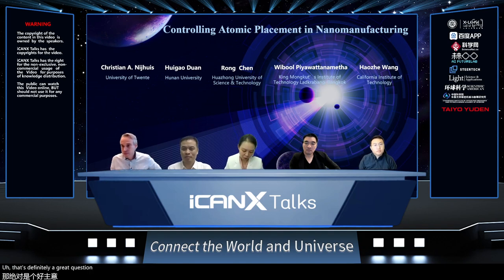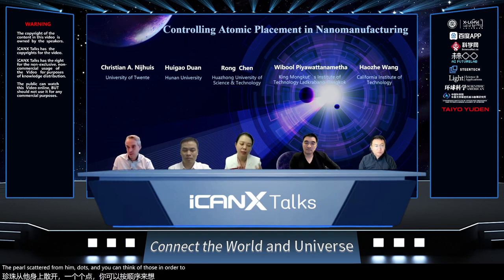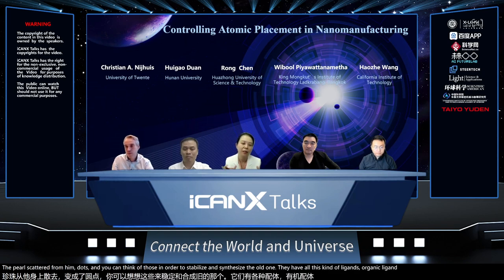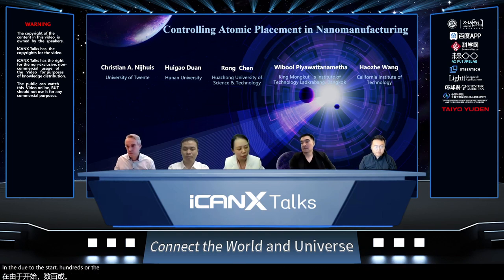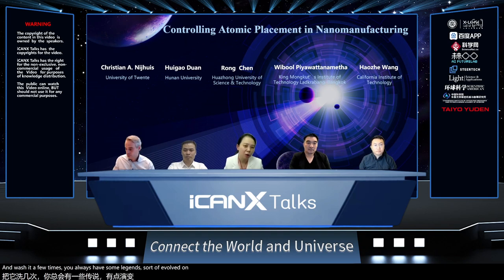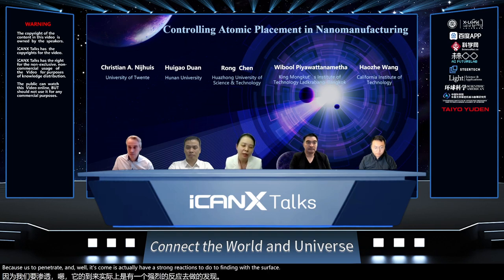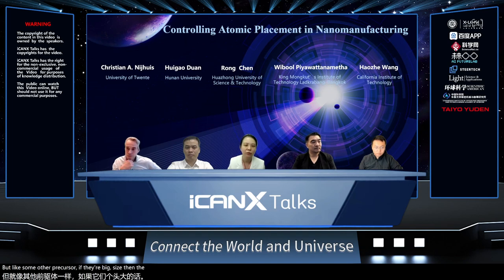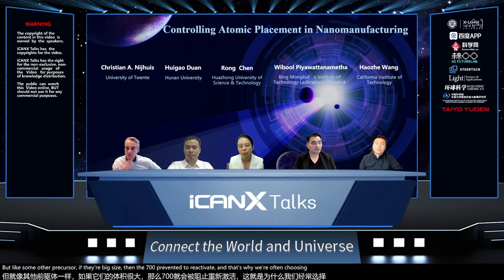That's definitely a great question. The quantum dots we are dealing with are mostly perovskite quantum dots. To stabilize and synthesize those, they have organic ligands passivating them. And due to the steric hindrance, or the process, you wash it a few times, and you always have some ligands dissolved or going away. So you leave a certain space, but that space allows small inorganic precursors to penetrate through. And once it comes in, it has a strong reaction to bind with the surface, and that actually helps passivate it very well. But with some other precursors, if they are big in size, then the steric hindrance would prevent them from reacting very well. And that's why we often choose small molecules to react.